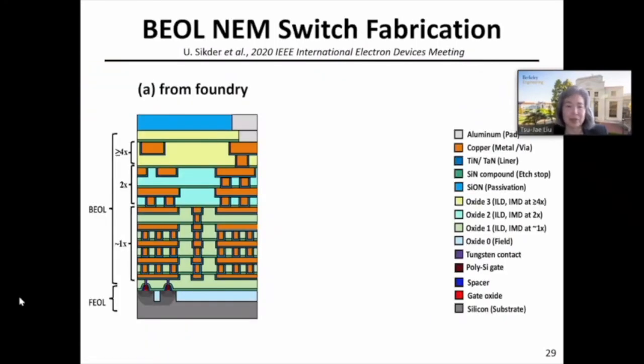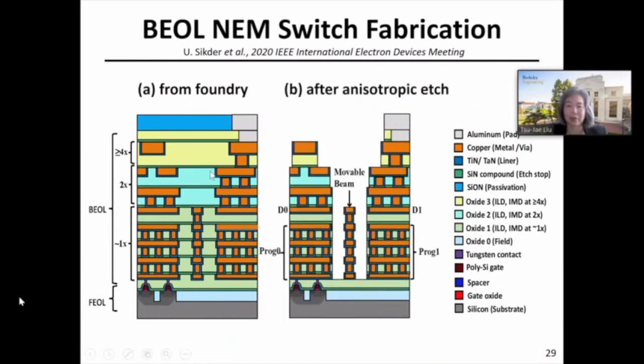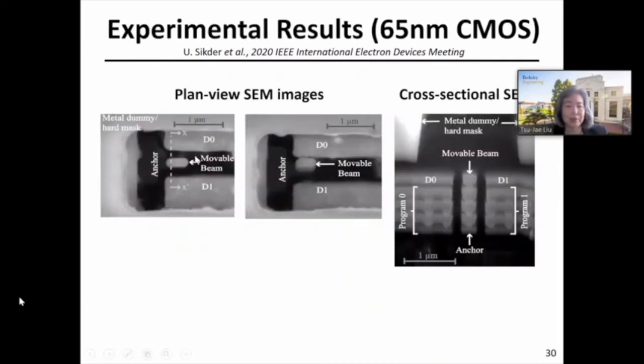So one of my PhD students has worked with standard foundry processes. Okay, conventional CMOS manufacturing process. What she's done is she's used the standard process development kit to design the metal layer patterns, so that they form that switch that I showed on the previous slide. And using the most tightly spaced metal layers to form the switch, the upper layers can be patterned to form a mask, so that after we get the chip back from the foundry, we can just subject this chip to an etch process to remove the dielectric layers on either side of the beam, and these upper metal patterns form a mask for that etch, so we can release that. So shown here are plan view scanning electron micrograph images of that switch. Here's the movable beam.